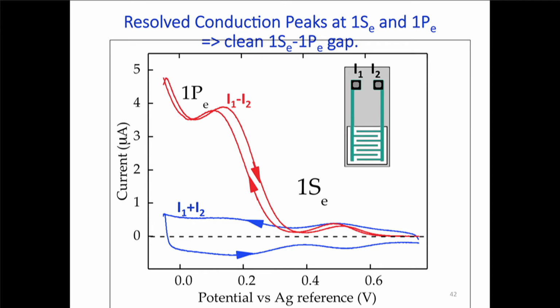So just to give you a little picture of what we do, this is the interdigitated electrode. We're going to put a film of dots on it. We put that inside a cell which contains electrolyte and a counter and reference electrode. And then we apply a bias with respect to the reference electrode, and we measure the current coming out of those two sets of digits. Conduction is the difference.